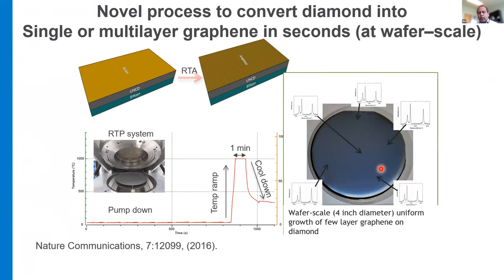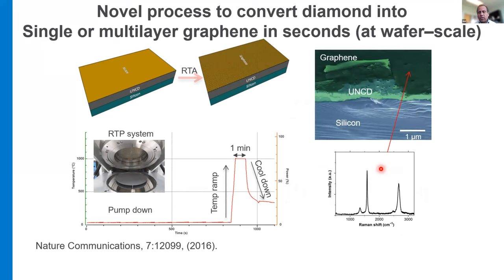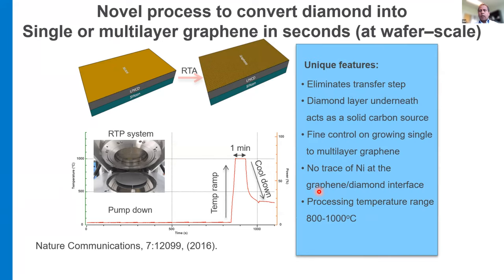And then what we saw is that you convert the top layer of the diamond into either few layer graphene or a single layer graphene based on the conditions of the annealing. If you see the cross section here in the false color, you can see the few layer graphene and the beautiful Raman spectra. The unique feature here is that the diamond layer underneath acts as a carbon source. And then you have fine control on growing either single or multi-layer graphene. Most importantly, there are no traces of nickel, so you don't have to etch the nickel from the top. And the operating temperature range is also pretty manageable, between 800 to 1000 degrees Celsius.